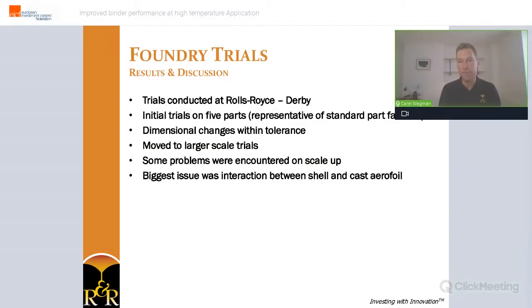As last evaluation, Rolls-Royce conducted trials with EHT in their Derby production plant. The first trials were conducted on five designs that represent the various families of castings at Rolls-Royce. The initial results showed that EHT was causing a slight dimensional change, but thanks to its improved shell build and strength, a reduction in coats was possible, and this put the dimensions back into acceptable tolerances.